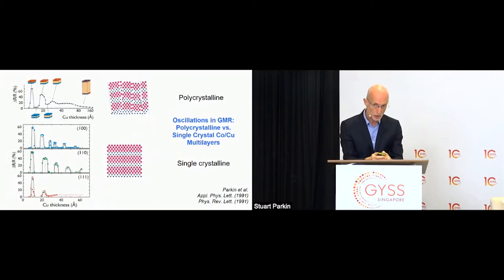And in this plot, you can see that the giant magnetoresistive value at room temperature oscillates from large values, for example, in the 100 direction of copper, 60%. When you change the copper layer thickness by just a few angstroms, then the giant magnetoresistance effect disappears. There's no change in resistance. When you increase the copper thickness a little bit more, then you establish the giant magnetoresistance effect again. So the magnitude of this effect oscillates as a function of increasing separation of the magnetic layers through copper. And this is something that I discovered and was the first to demonstrate.